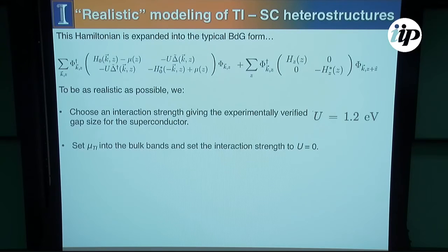Furthermore, at least when we started these experiments, it was very difficult to get the chemical potential of the topological insulator into the gap regime. It was always up in the bulk bands. So to be consistent with that, for the topological insulator, we set the chemical potential up into the bulk bands. And because it's a topological insulator and not inherently a superconductor, we set the pairing inside of the topological insulator to be 0.